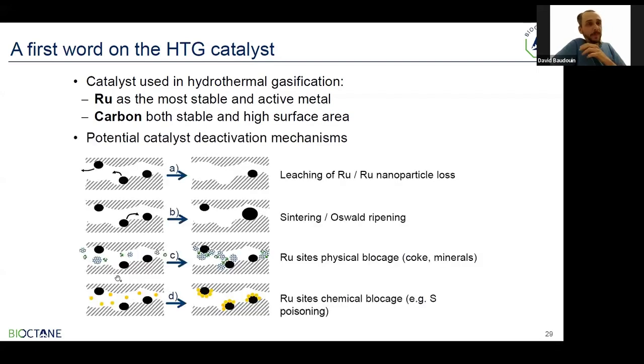Next slide, please. Here I list the main deactivation mechanisms that the catalyst can suffer from under these conditions. Of course, there are lots of similarities with gas phase catalysis in other applications. You have leaching of ruthenium, or loss of ruthenium through debris of catalyst being flushed away from the bed. You have sintering, Ostwald ripening, different mechanisms leading to loss of surface area of the metal. You have physical blockage of the metal, and of course poisoning of the active metal by sulfur or other elements.